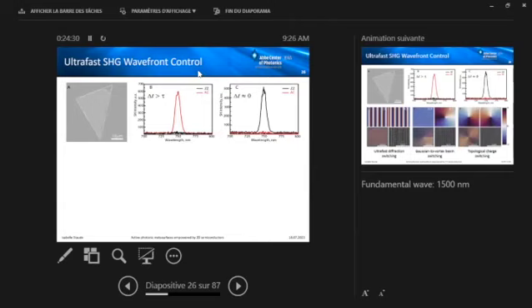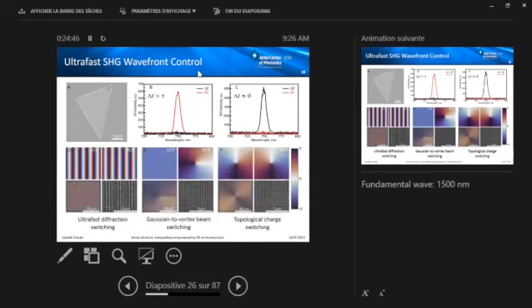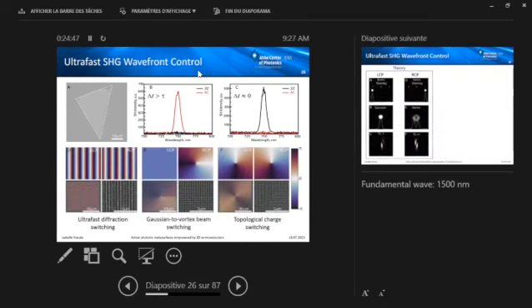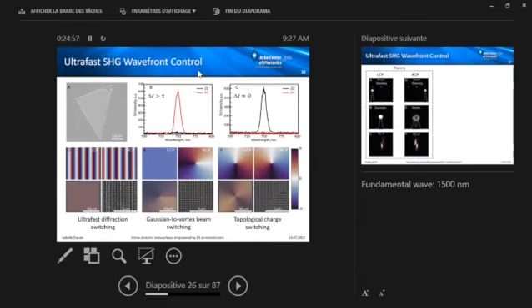Here's some details of the experiment. This is the flake. We used the WSe2 monolayer. We reproduced this ultrafast switching of the polarization of the second harmonic at 1550 nanometer for this material. And we also designed such metasurfaces for ultrafast diffraction switching, Gaussian to vortex beam switching, and opposite topological charge switching here. And I give you here in the top row, these are the phase masks for left-handed and right-handed circular polarizations that we're implementing. And then you always see, for each metasurface here, a light microscope image and a scanning electron micrograph of the system.